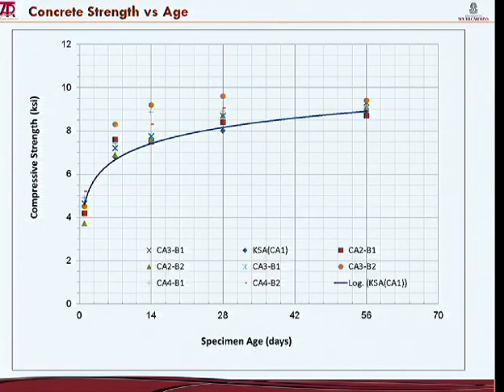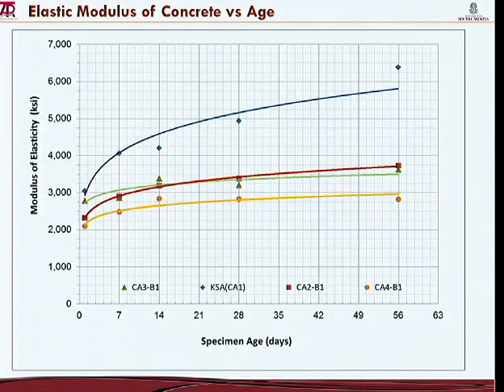When we looked at the modulus of elasticity versus age, we see that the standard design follows the trend in the models that we're all familiar with. However, for the weathered granites, the modulus did not pick up. At early times you see a relatively small difference between the moduli, but it looks like a good wine: the older it gets, the better it behaves, or tastes. Okay, so we see higher reductions of the modulus at later times.